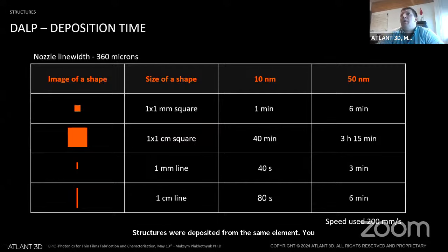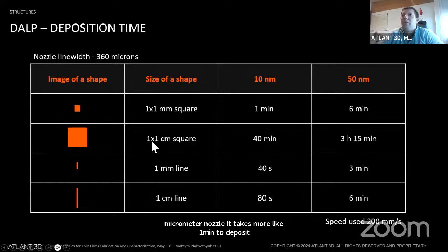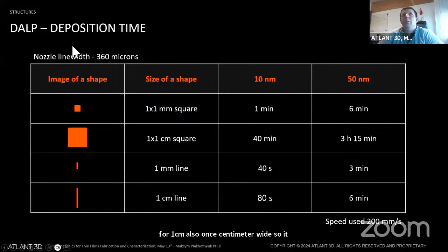You might ask, well, how much time does it take to process? Depends, of course, on the micro nozzle, but 1 millimeter square, for example, if it's used with 360 micrometer nozzle, it takes like 1 minute to deposit, or 50 nanometers, 6 minutes. And the nozzle can be made for 1 centimeter, also 1 centimeter wide. So it also would take 1 minute, but for 360 micrometers, it's like 40 minutes.